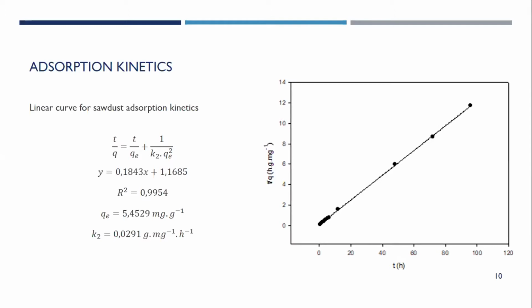Regarding Sawdust, the same linear curve was constructed based on the same equation. For an initial concentration also of 50 milligrams per liter, the Sawdust adsorptive capability was 5.4529 milligrams of dye per gram of adsorbent, while its constant for pseudo-second order adsorption rate was 0.0291, which shows that in relation to Chitosan, Sawdust has a lower adsorptive capability and also a much lower adsorption rate.